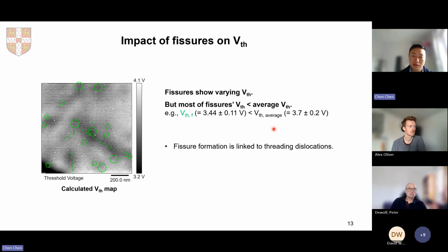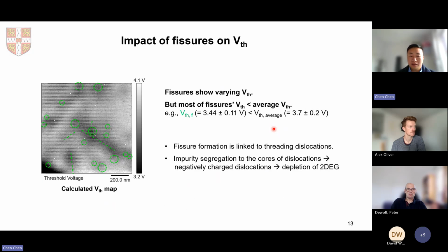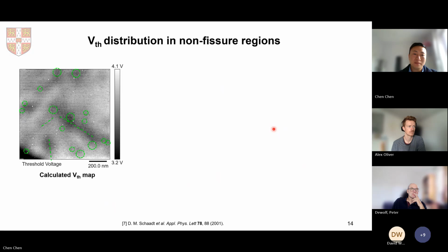What could be the reason that most fissures reduce the local threshold voltage? One potential reason is that fissure formation is linked to threading dislocations. For these threading dislocation-linked fissures, impurity segregation could happen at the dislocations, making the dislocation negatively charged, and hence the local 2DEG is depleted, resulting in a lower local threshold voltage value.